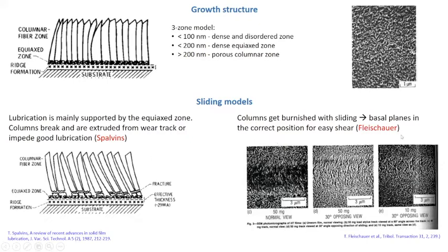Opposite to this scenario, we have the opinion of Fleischauer, who says that the presence of the columns here is mandatory in order to have good tribological performance, because he foresaw that the sliding of the counterbody induces the bending of these columns in order to align the basal planes to the sliding direction. And if you look at these images from his work, you can clearly see what he wanted to communicate, that the sliding of the counterbody induced the bending of the columns in order to improve the tribological performances of the material.